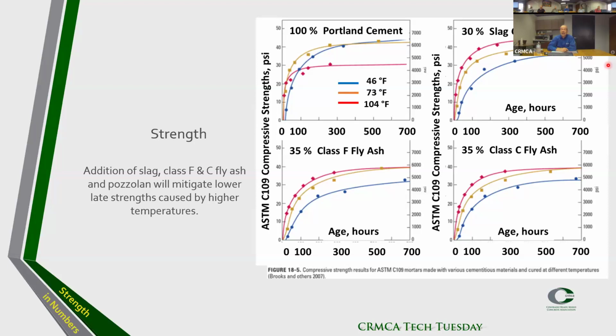What we see is with slag, an F ash or a C ash, they help compensate because they slow down the hydration process in the very beginning, and they do this so that they help mitigate lower strengths later on. So again, SCMs are beneficial if we have higher temperatures in concrete.